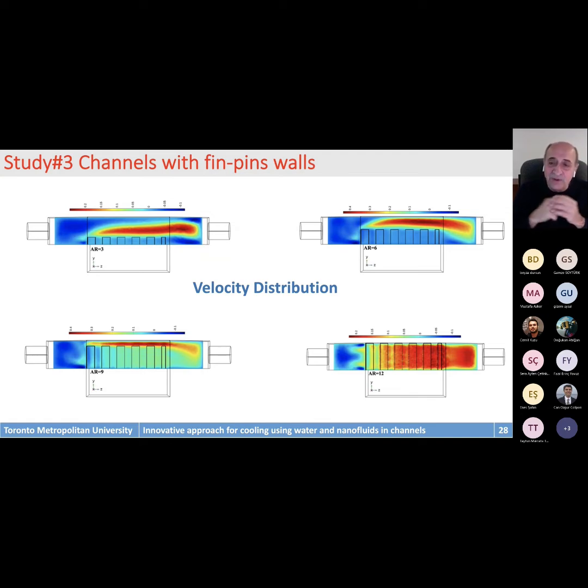And by varying the height, we are encouraging the flow to circulate above the pin fin, and for the flow to circulate between the pin fins, and then they mix. And this is why we love to have mixing, because mixing will enhance the heat transfer without switching to turbulent flow. And this is obvious from this particular one, whereby when you have a full height of the pin fin, flow follows a certain pattern like a channel. However, when the height is changing, we see some circulation on the top and on the side.